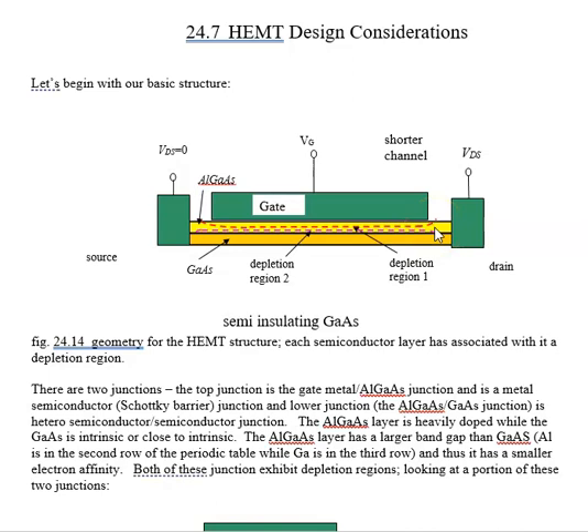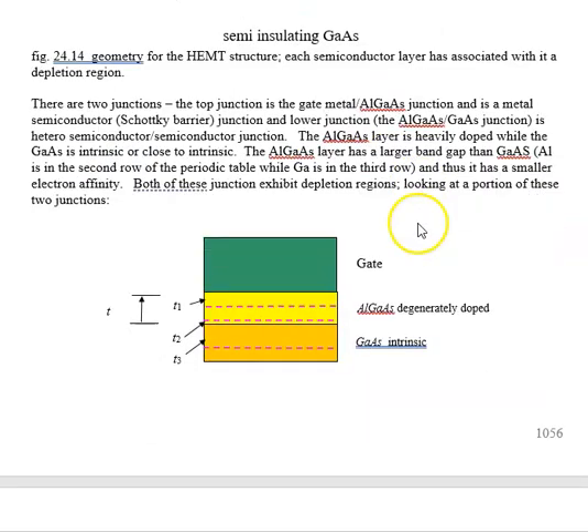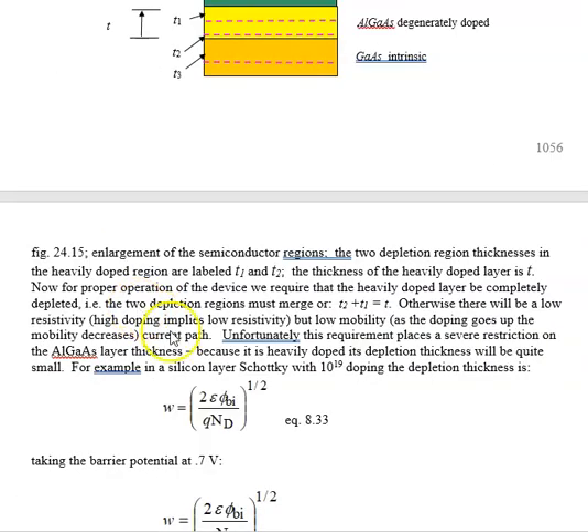Because it may be low resistivity, but it is also very low mobility. And so we'd like these two regions to merge. In other words, we want the yellow region to be completely depleted. And in order to do that, we want T1 and T2 to add up to T. And if we do the relatively simple calculations, we have degenerate doping of about 10 to the 19th.